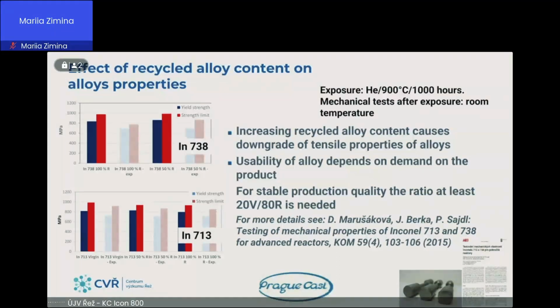As-received samples and also exposed samples were tested and some differences were recorded. The conclusion of this investigation was that revert materials influence the quality of the cast alloy, and for stable production quality a ratio of at least 20% virgin material must be maintained. More details you can read in the paper which was published with Daniela.